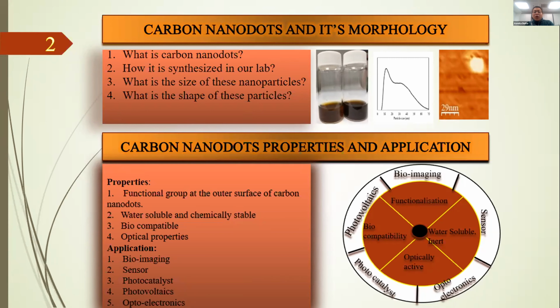About size, all I can say is that our lab-synthesized CND has a size distribution from 10 nanometers to 70 nanometers, as you can see in the DLS graph. It has a spherical shape, as you can see in the AFM image.